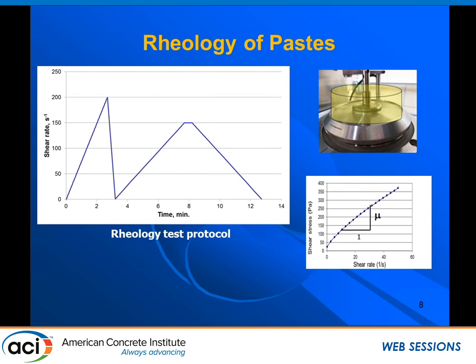So we ran rheology. Our rheology test protocol was: we had a pre-shear, then we increased the shear in 10 steps, and then we decreased the shear in 10 steps. We used this curve to plot shear stress over shear rate. With this curve, I have the slope as apparent viscosity, and the intercept is our yield stress.